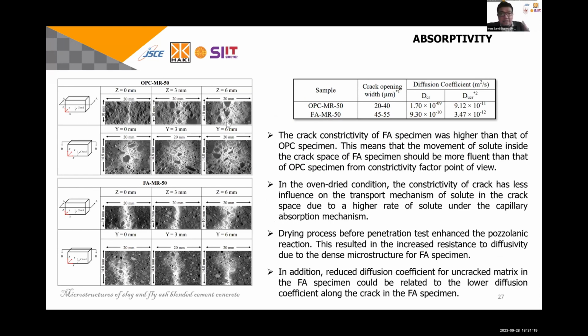And then for the last part of my presentation, the absorptivity test. This is from a flexural tensile specimen. The crack was generated by flexural load, and as you can see here, for the OPC, the tracer spreads out into the specimen, not only in the crack but also the uncracked matrix. But for the fly ash, as you can see, the spread is smaller compared to the OPC. Here, we can conclude that the reduction in diffusion coefficient for uncracked matrix in fly ash specimen could be related to the lower diffusion coefficient along the crack.